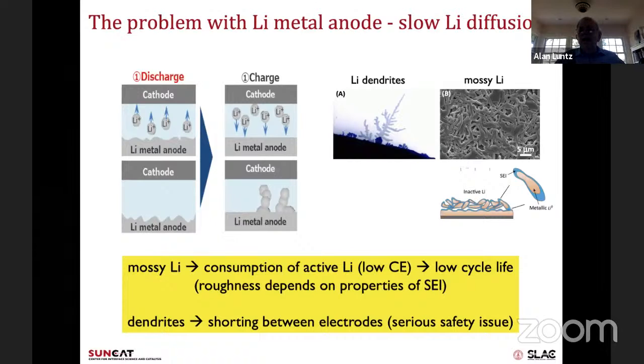It's very rough, has a lot of surface area, so it consumes a lot of the lithium in the electrolyte, making the SEI. The other thing is a lot of the lithium metal that you've produced now is coated with the SEI, so it's not in electrical contact with the current collector. So it's called dead lithium. It's isolated, it's passivated. So all of these things lead to consumption of the active lithium at a low coulombic efficiency. So that's the main problem. And of course, that means a low cycle life.